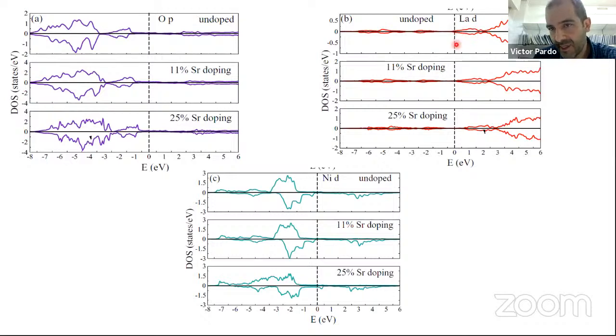One more ingredient: the lanthanum bands move higher in energy. That means that when you start doping with strontium, the self-doping effect, this is the partial occupation of the rare earth band, just disappears. The bands move higher, away from the Fermi level, and the self-doping effect that occurs in the undoped compound is not happening when you dope it. So this was an ingredient that was making these materials different from the cuprates. When you dope it, these nickelates become more cuprate-like.